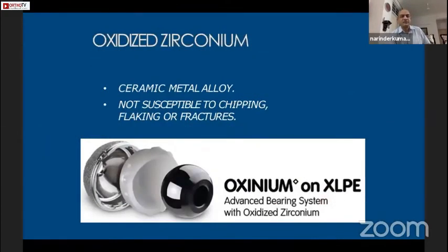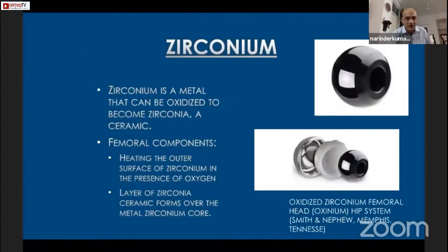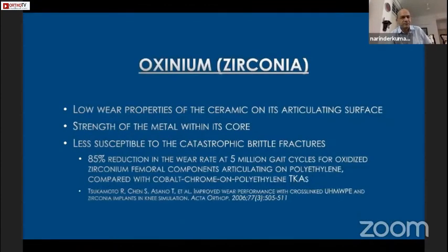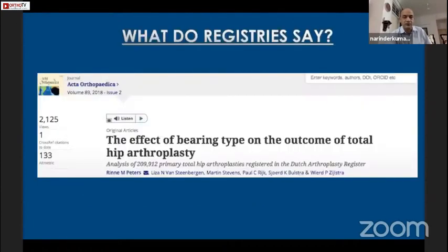And the final option, the oxidized zirconium, the ceramic metal alloy, which is patented by Smith & Nephew, so I will not be encouraging about it too much, but it is a metal that can be oxidized, which becomes zirconia on the surface. You heat the outer surface, which becomes now the patented name called Oxinium, the oxidized zirconium femoral head. It has similar properties like ceramic, low wear properties, but the advantage of the strength of the metal within its core. So it becomes less susceptible to the brittle fractures which ceramics were actually susceptible to.